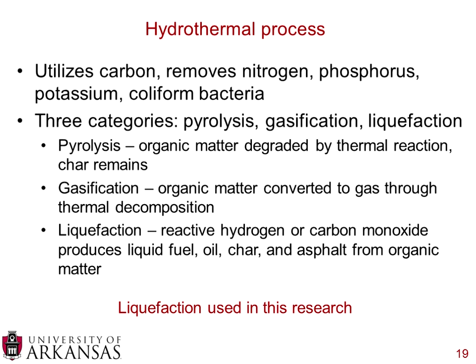And then finally, liquefaction, which is the most useful for this research, is where you use reactive hydrogen or carbon monoxide, and you're able to produce either liquid fuel, liquid oil, solid char, or some sort of asphalt type material from the organic matter. So by using this hydrogen and carbon monoxide, you go through this hydrothermal process, and one of the byproducts from that is an asphalt type material, and that's what was used for this research.